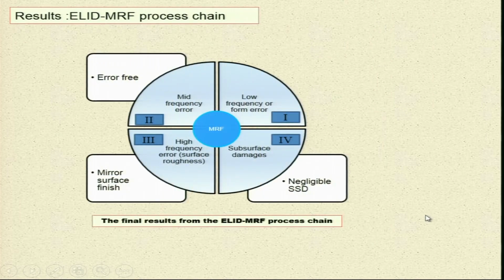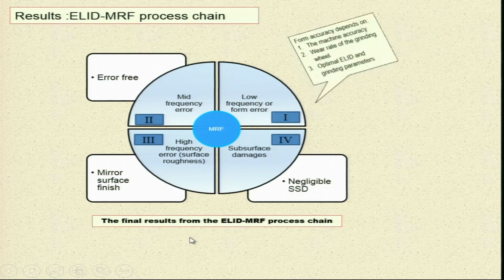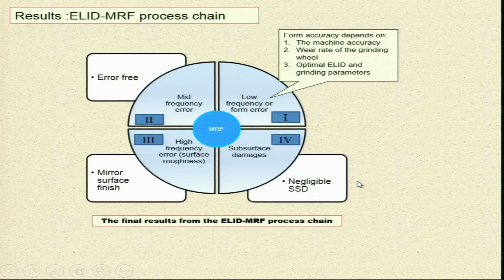These are the results of the ELID MRF process. Error free, mirror surface finish is obtained, negligible subsurface damage is there: mid frequency error, low frequency or form error, high frequency error, surface roughness and subsurface damages. The final results from the ELID MRF process chain: form accuracy depends on the machine accuracy, wear rate of the grinding wheel and optimal ELID and grinding parameters. Applications.